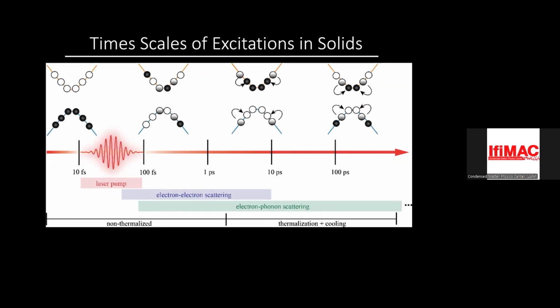remember what a femtosecond is, it's 10 to the minus 15 seconds, right? Over slightly longer time scales of picoseconds, you have electron phonon scattering. And now is when the system starts to get thermalized. Because until you have just the electron-electron scattering processes, the electrons are really, really hot. You can imagine they're thousands of kelvins, but the solid is not hot because the atoms are not yet vibrating. But then once the electrons scatter with the atoms, then the atoms start getting heated up. Now, the atoms are much fatter than the electrons, so the actual temperature of the sample really doesn't go up very much. But initially, the electrons are really hot. Anyway, so this thermalization occurs over femtoseconds to picosecond time scales.